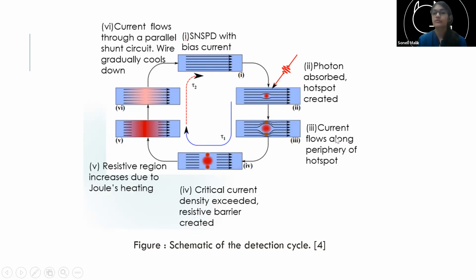Now, because we're so close to the critical current already, in these regions where the current starts flowing, the current density exceeds the critical current density, the maximum that the superconductor can handle. So because the critical current density has been exceeded, the whole width of the nanowire will cease from being a superconductor. And you have a resistance across the whole width, which means current flow will stop. There is a parallel circuit to our single SNSPD, which has a resistance less than what we expect here.